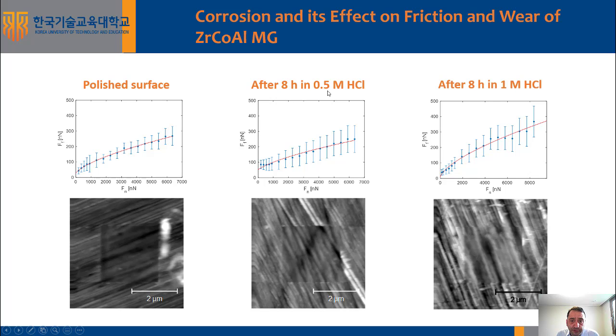After immersion for 8 hours in 0.5 mole per liter hydrochloric acid, we again do not see much change on the surface. In fact, the determined shear strengths remain the same, in the range of 1 gigapascal, and again a similar result after immersion in 1 molar solution of hydrochloric acid.